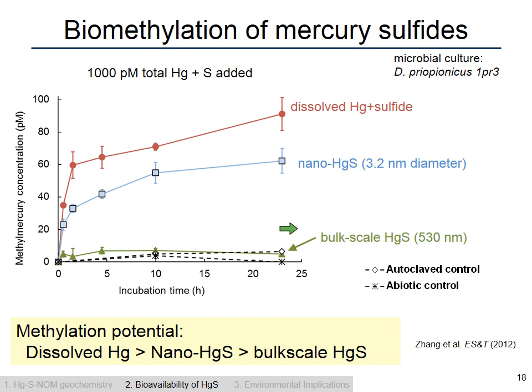And what you can see is that we have the greatest amount of methylmercury produced over time with the dissolved treatment, an intermediate amount of methylmercury produced with the nanoparticle treatment, and then hardly any methylmercury produced with the bulk scale metacinnabar, not significantly different from our abiotic controls. So there's definitely a gradient in methylation potential depending on what kind of mercuric sulfide you're dealing with.